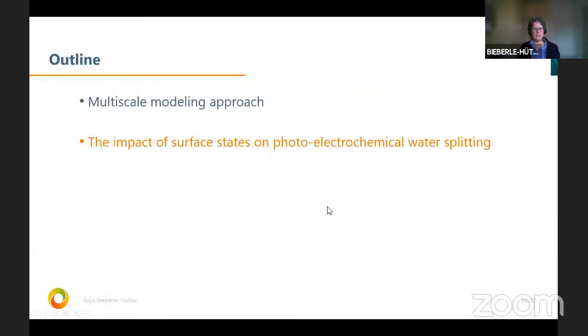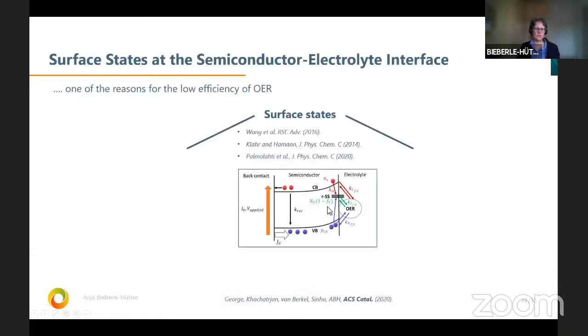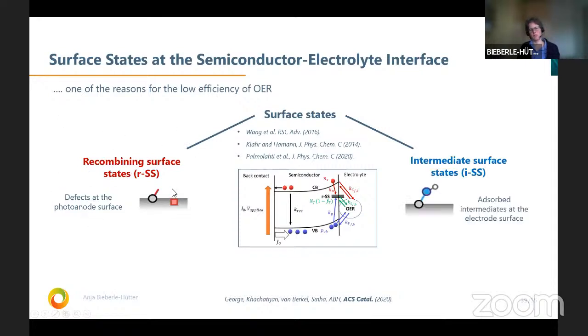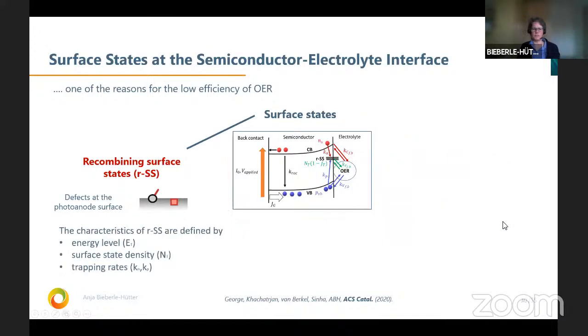And this is actually the second part. We looked a bit at the surface state discussion, because this is one reason why we have low efficiency. We have different kinds of surface states, these so-called recombining surface states, which are defects at the photoanode surface, and we have intermediate surface states. We take the nomenclature of these surface states from the literature here, which are adsorbed intermediate species at the electrode surface. So the characteristics of these recombining surface states are energy level, surface state density, trapping rates.